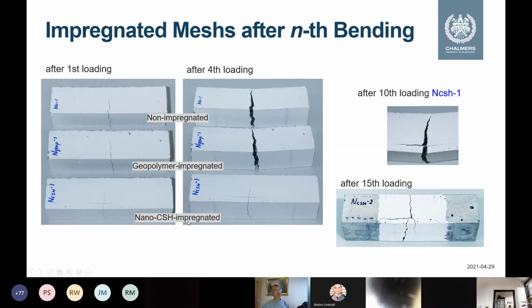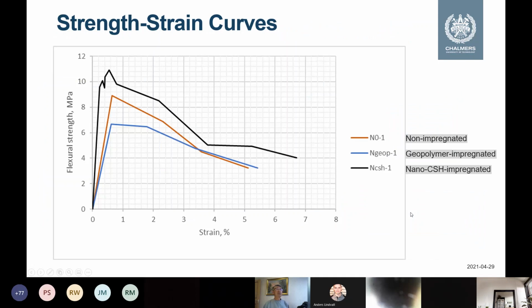The nano impregnated fiber does not break until the 10th loading. This is at 7 days, and this is at 28 days. Even after the 15th loading it does not break, and it is still whole. Here is the result, you can see the curve. It can deform even more, with strain up to 6%, which is quite high.